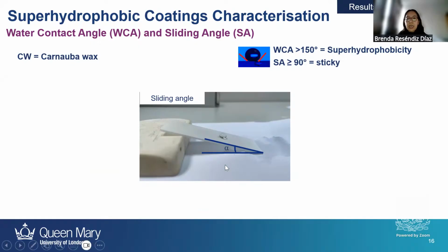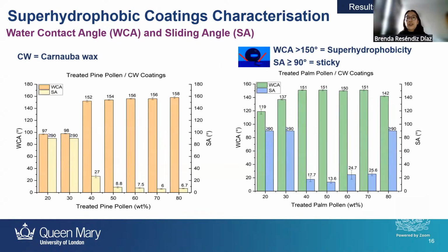So here is how we calculate the sliding angle. Actually, it's the position of how we tilt the surface. I measured the water contact angle of pine pollen Carnauba wax combinations and palm pollen Carnauba wax combinations. As we can observe, when I use 80% to 40% weight percentage of pine pollen, we have contact angles above 150. When I increase the amount of wax, I get a flatter surface, so it's more sticky and the water droplets don't roll easily.